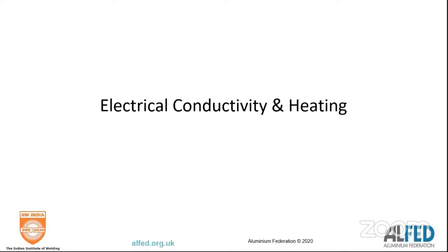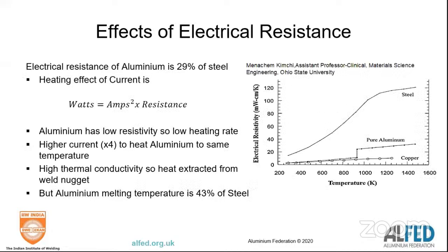We're moving on at pace, but I know you are very, very keen to learn. So let's talk about electrical conductivity, and let me start off with a little bit of theory. The heating of aluminium by a current is amps squared times resistance. The first problem you have is that aluminium has low resistivity, so amps squared times resistance gives you a low heating rate. You require a much higher current, about 4 times that of steel, to heat aluminium to the same temperature, but you've got high thermal conductivity, so heat is going to be extracted. And never forget that aluminium has a low melting point.